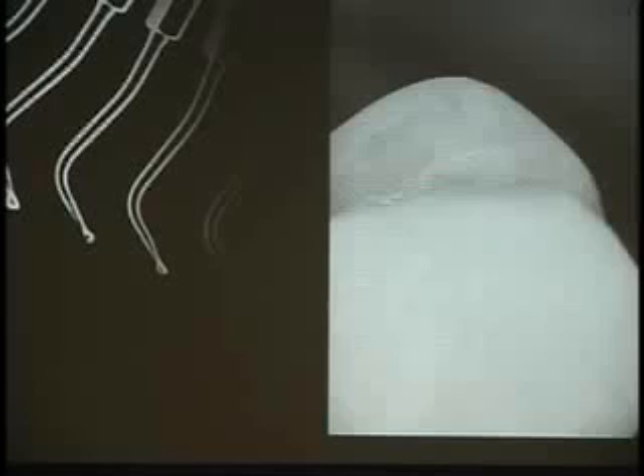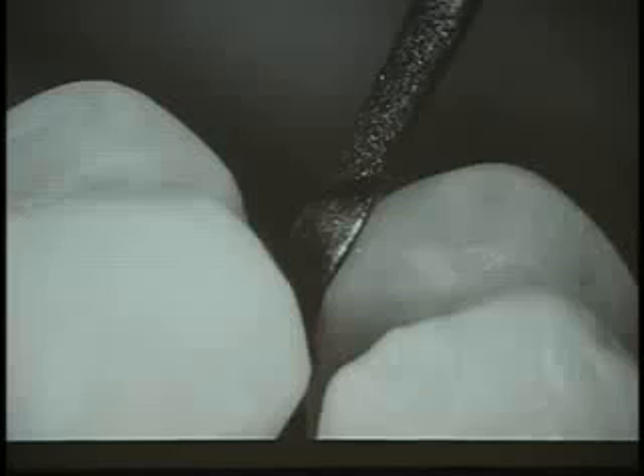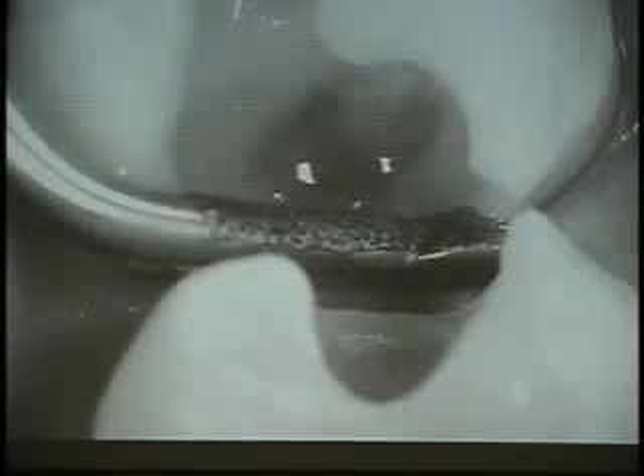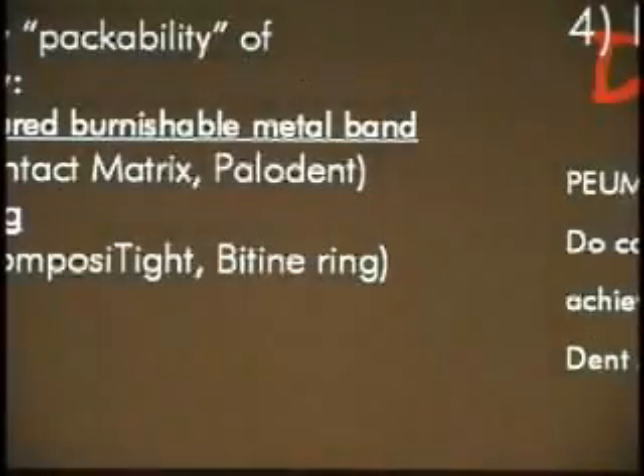You can cut with this tip micro cavities for very small decay in the most ultra-conservative way. What is recommended here is to cut the proximal cavity without removing the enamel wall. You keep the very thin enamel wall intact, and then you go with this instrument and finish the proximal aspect, and you can have a very clean cut. Another instrument that is really nice is like a cone with a 45-degree angle, and this one will make a perfect bevel of your enamel, as you can see here, with absolutely no risk of touching the neighboring tooth. I think this is a great tool we really have to implement.